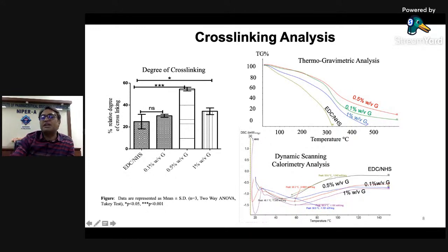A similar trend was seen in the differential scanning calorimetric analysis, again showing the incorporation of both groups, and 0.5% looks fairly good compared to the collagen-only material.